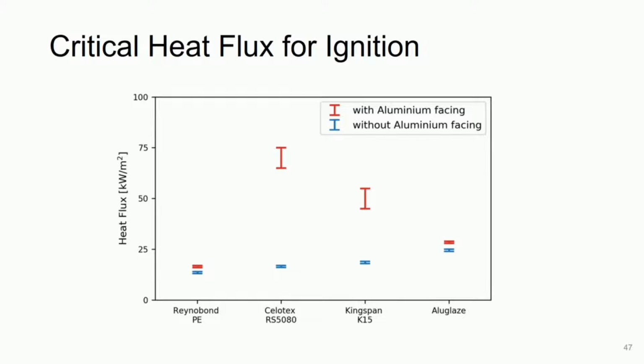At the high end, a heat flux exposure of 75 to 100 kilowatts per square meter is in the range of the severities of heating that would be expected over the first 1 to 2 meters above the hearth in a BS 8414 large-scale cladding test, as Professor Torero mentioned this morning. It's noteworthy that all 4 of the products listed in this plot are metal-faced polymers, but that the thermal and physical properties of both the metal facers and the polymer cores differ substantially. And you can see I'm plotting results both with and without the aluminium facers.